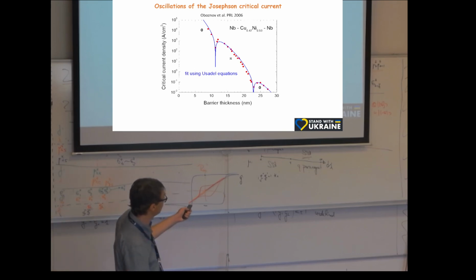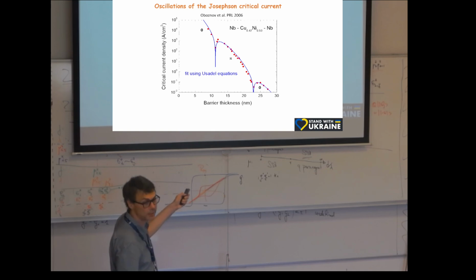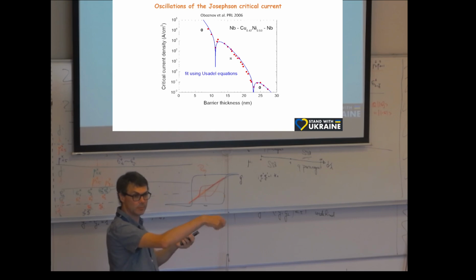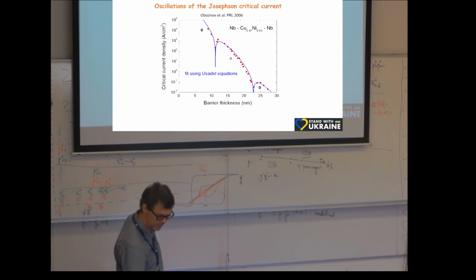And you can see, somebody asked what is the thickness. This is the 30 nanometer thickness. It's a disordered alloy, so it's a lot of scattering. Maybe every second atom you scatter. It's a very disordered, very diffusive regime. And so you have to use these Usadel equations, which I'm not going to talk about, but you can look it up.